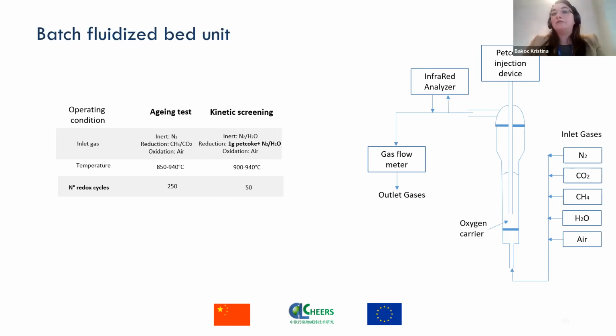And again, the outlet gases would be analyzed with the same infrared analyzer, and the outlet flow rates would be measured as well. In this case, we wanted to check for the performance of the oxygen carrier with the actual solid fuel, where there is an additional step of Petcoke gasification, and that can significantly influence the kinetics of the overall system.